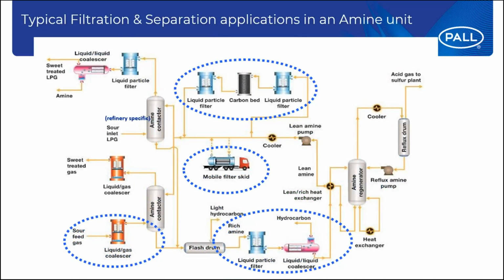We see here a typical P&ID of an amine unit, where you have typically a contactor or absorber to sweeten the sour gas, and then you have the amine solvent loop with amine regeneration in order to guarantee the cycles and that the amine has had all the acid removed from it, and it can start a new cycle of sweetening. We have here, as you see highlighted in blue, 4 locations where a filtration, a separation solution is handy, and it can help to bring the cleanliness of the amine loop to low sustained levels.